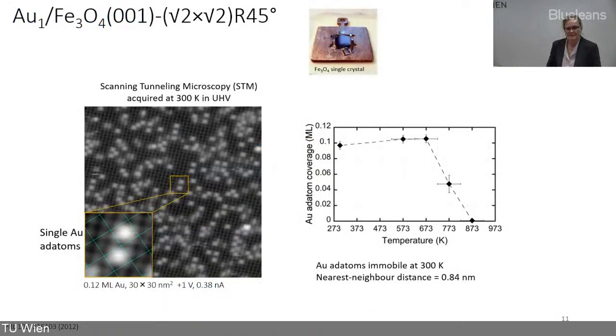Okay, so this is a result from 2012, where we looked at an Fe3O4 magnetite, an iron oxide single crystal, shown in the upper right. It's a single crystal prepared in this special way that we have in ultra-high vacuum surface science. When we evaporated gold atoms on it, we had a real surprise, because normally gold is very diffusive - gold immediately makes clusters at room temperature. But on this particular surface, each gold atom was stuck individually. So these bright spots you see in this image, each one is one individual gold atom that sits at a very specific site on the surface.